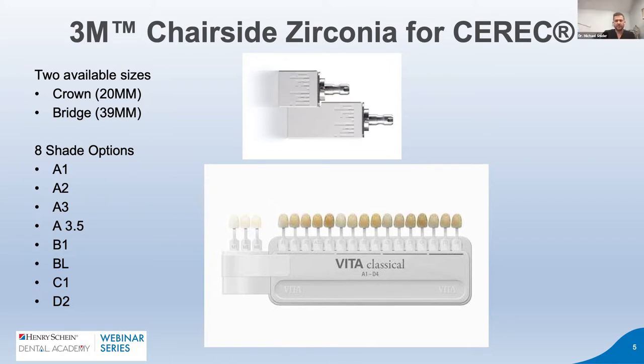Most of the time my team is hand polishing these restorations after firing, and hand polished restorations tend to be pretty true to the Vita Shade system. However, if you're going to be glazing these restorations, they come out a little higher in value. So if we decide to glaze a zirconia restoration, we'll usually step down one shade, because the glaze makes it appear more bright or higher value in the mouth.